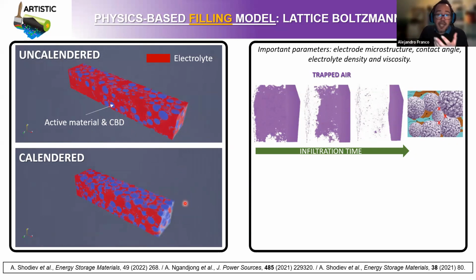So this is highlighting that there is a trade-off between the manufacturing process step calendering and the manufacturing process step electrolyte infiltration, because in the calendering, you need to compress the electrode in order to improve the electronic contact between the particles. But in electrolyte infiltration, it will be better to have high porosity, right? But if you compress the electrode, you will have lower porosity, you see? So it's very important to optimize both steps by considering both of them, right? That's why this kind of modeling workflow, where we intend to capture different model tools sequentially, is very useful, because otherwise you cannot reveal these kinds of correlations between different process steps.